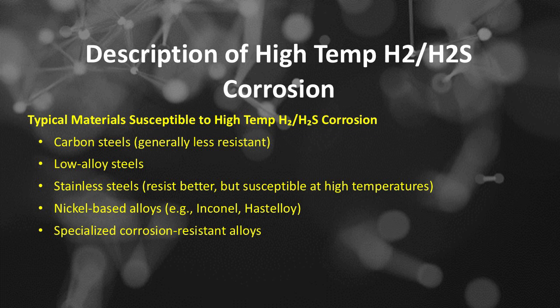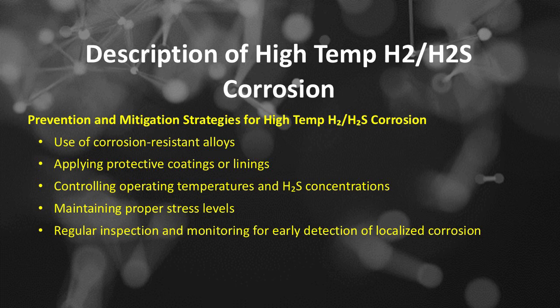Typical materials susceptible to high-temperature hydrogen or H2 and hydrogen sulfide or H₂S corrosion include carbon steels, generally less resistant; low-alloy steels; stainless steels, which resist better but are susceptible at high temperatures; and nickel-based alloys, such as Inconel and Hastelloy, specialized corrosion-resistant alloys. Prevention and mitigation strategies include use of corrosion-resistant alloys, applying protective coatings or linings, controlling operating temperatures and hydrogen sulfide or H₂S concentrations, maintaining proper stress levels, and regular inspection and monitoring for early detection of localized corrosion.